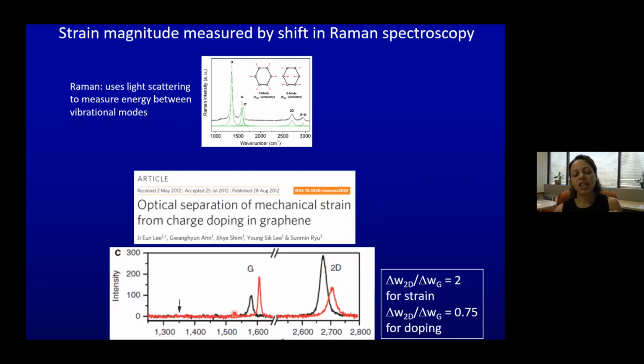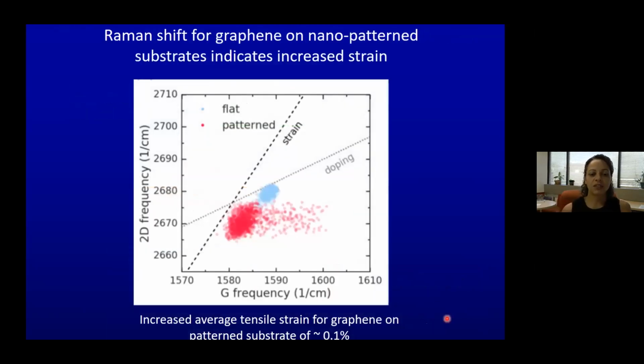Okay, so if the ratio of the shift of the 2D to the G is 2, then that means that you're straining the graphene. If the ratio of the shift of 2D to G is 3/4, then it means you're doping the graphene. So now we have a way of optically determining whether the graphene is strained or doped, and by how much, just looking spectroscopically. And so this is what we did on our devices.